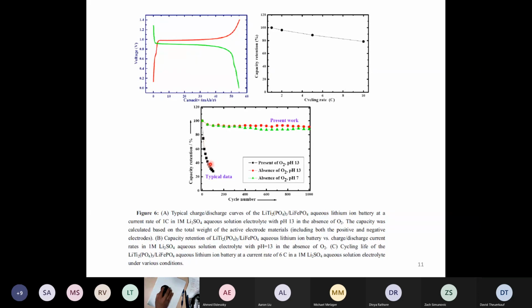So this is another thing that we did not recognize when we were working on the system, lithium manganese oxide and vanadium oxide. We didn't realize the importance of oxygen in the electrolyte. So it would be kind of neat to go back to that old system and see what happened if you de-aerated the electrolyte before you started your cells. So this just shows that you can make a pretty good aqueous lithium ion cell with the right electrolytes and the right electrode materials. They're going to have fairly low voltage if you want to stay within the water stability window.